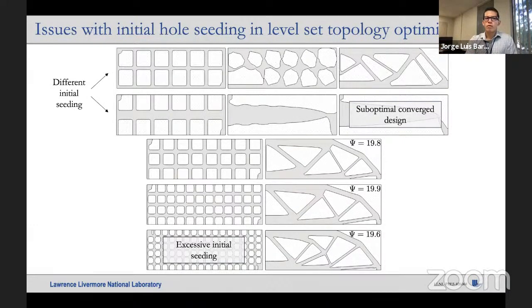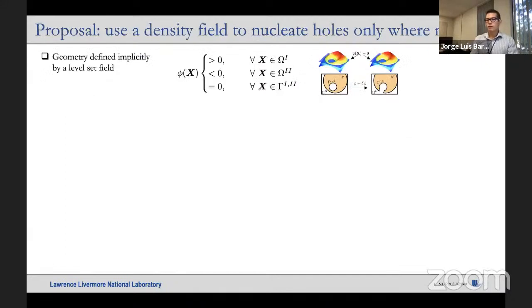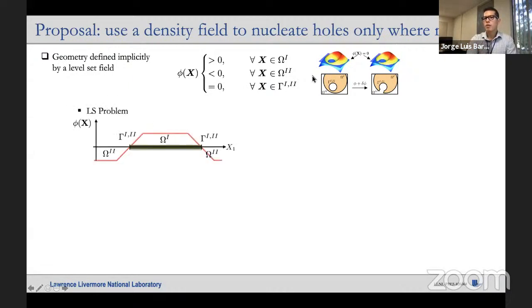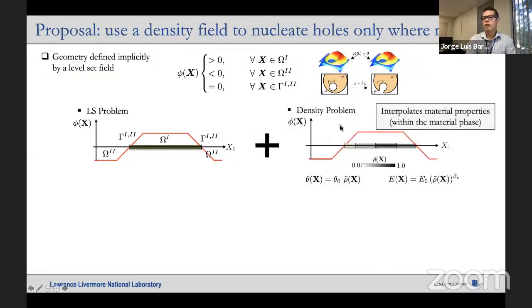So what we proposed in this work was to use a density field to inform the level set problem and nucleate holes only where needed. The starting point is the typical level set formulation in which everything above your level set field is material, everything below the level set field is void, and the interface is defined by the zero isocontour. So what we do here is that on top of this, we include a density problem within the material phase.